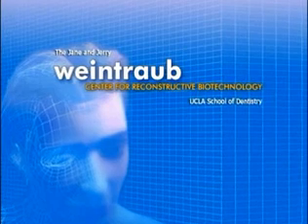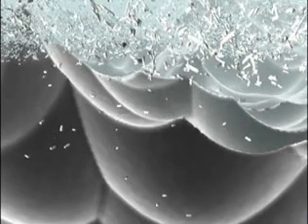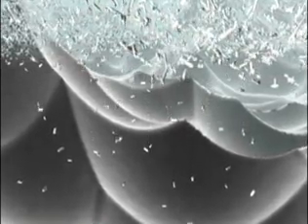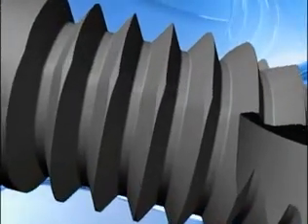Calcium phosphate is a well-known biomaterial in implant dentistry. Could it, at a nanoscale, optimize the surface? The biological effect of the prototype nanoscale calcium phosphate deposition was initially being studied by researchers in the UCLA School of Dentistry's Jane and Jerry Weintraub Center for Reconstructive Biotechnology in Los Angeles, California. That's the process of depositing nanoscale calcium phosphate crystals on the surface of an implant. However, the crystals are so small that scientists need to use advanced high-resolution scanning electron microscopy at high magnification to visualize the details. Biomet 3i, using state-of-the-art field emission scan microscopy, was able to visualize the deposited surface and noted that it was not a layer or a coating, but actually a discrete crystalline deposition, or DCD.